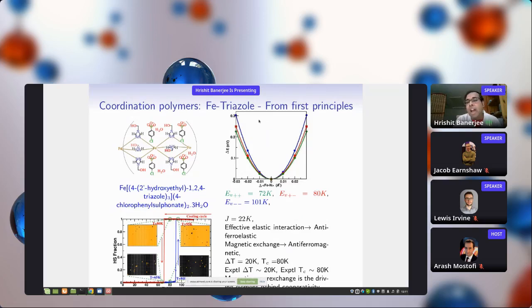We take the example of iron triazole, and from first principles calculations, we calculate the elastic interactions, and we calculate the E++, E+-, and E-- by fitting the energy versus iron-nitrogen bond length, and we find that this is an antiferroelastic interaction. And when we plug these back into our Monte Carlo model, and then we obviously need the magnetic exchange, when we plug also the magnetic exchange back into the model, we find that we can very well reproduce the experimental delta T, that is the width of the transition, and the TC, which is the central point of the transition, very well.